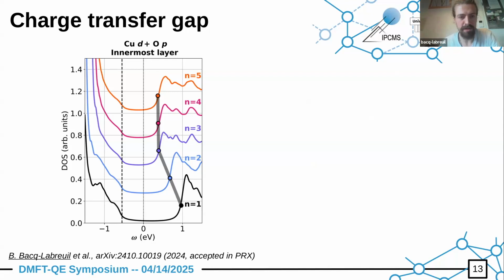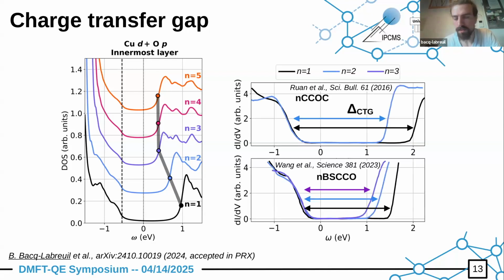from the tri-layer compound. We can compare that directly to experiments. That's quite nice. We have some STM data from two different papers. One is for the NCCOC, so the very same compound. And you can see that there is also a very nice reduction of the charge transfer gap from n equal 1 to n equal 2 of the same order of magnitude. So here it's 500 millielectron volt. In the calculation, it's rather 300 millielectron volt, but it's the very same order of magnitude. And for the n equal 3 compound, we don't have data for NCCOC, unfortunately, but we have them for the bismuth-based superconductors. And you can see that there is indeed a further reduction of this gap from n equal 2 to n equal 3. So this seems to match quite well.